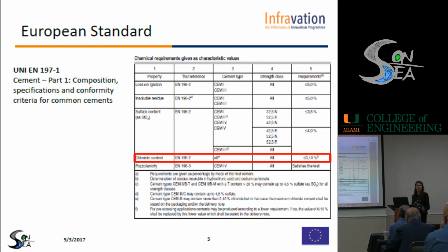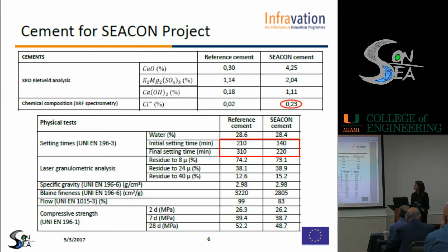So in particular, when we use waste material as an addition in cement, we have to control this limit carefully. Here, there are two cements that we consider in the study: a reference cement, a Portland cement 42.5 that is commonly produced and sold in Italy, then SEACON cement. We produced a dedicated cement, as I already told you, for this project, using, in this case, cement kiln dust in partial substitution of natural limestone.